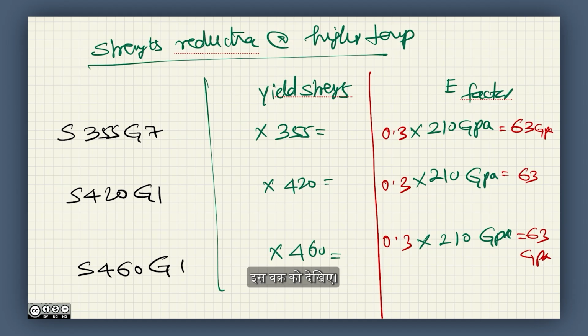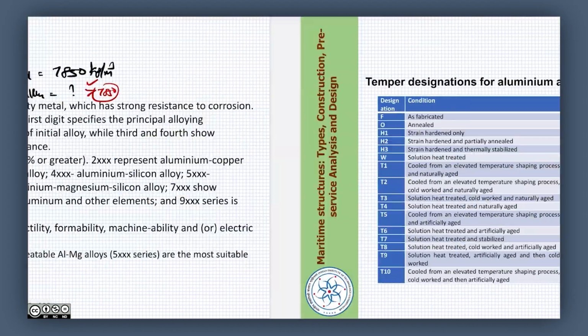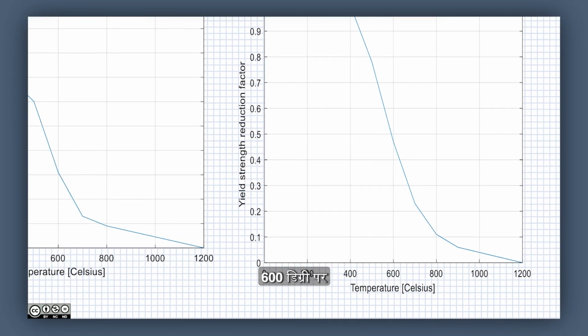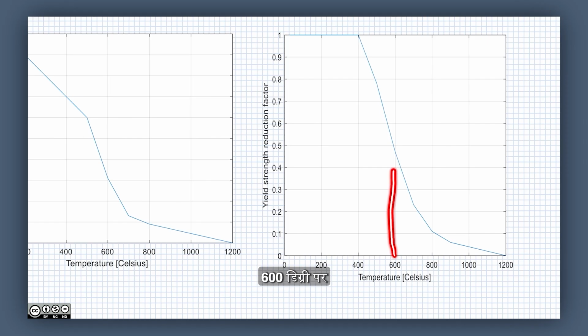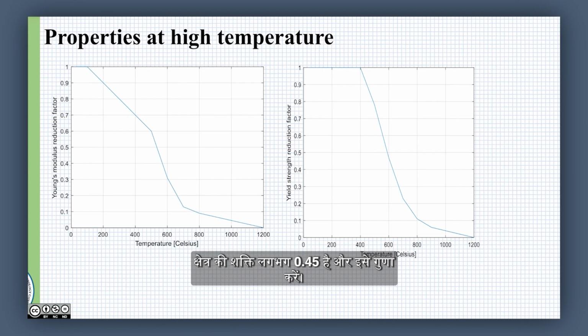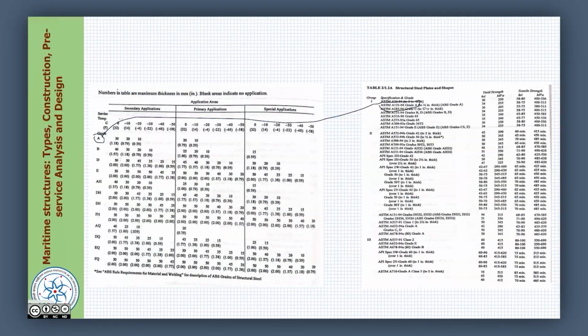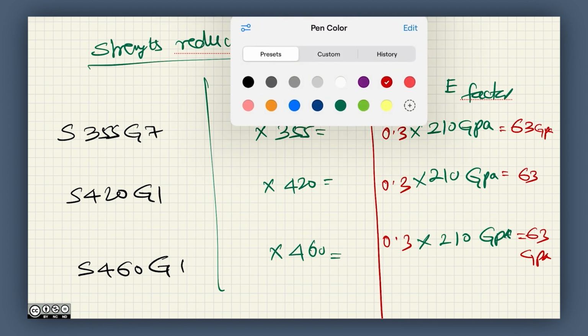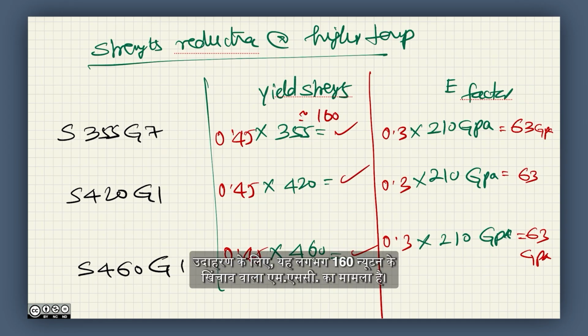Similarly, let us look at higher temperature and work out the yield strength. Look at this curve, the yield strength part. At 600 degree, the yield strength factor is about 0.45. So, I multiply with 0.45 for each steel, and I can get these values. For example, this is about 160 Newton per mm square. Friends, there is a degradation of yield and Young's modulus. You cannot use a standard number for the design when used at higher temperature. Be very careful about that.